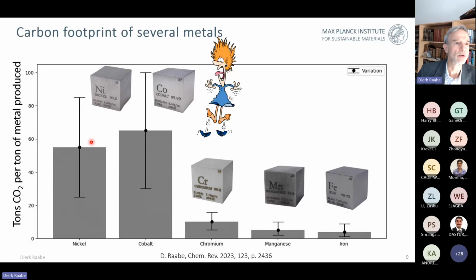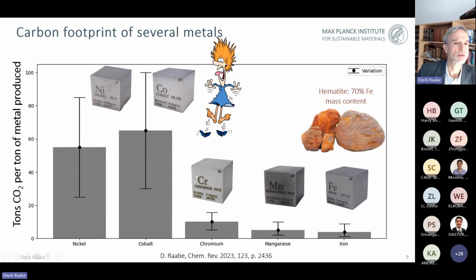When you compare that with nickel or cobalt or the other elements, then these numbers can be in part much, much bigger. That has, of course, to do with the strength of the chemical bond between the oxygen or the sulfur with the corresponding transition metal. But it also has to do a lot with the fact that some of the minerals, particularly those that we use for iron making, are actually quite pure.